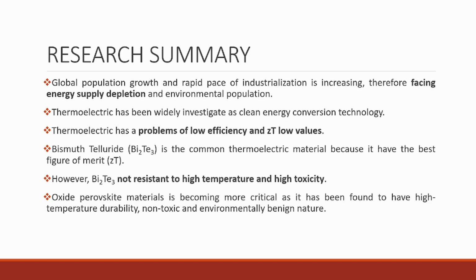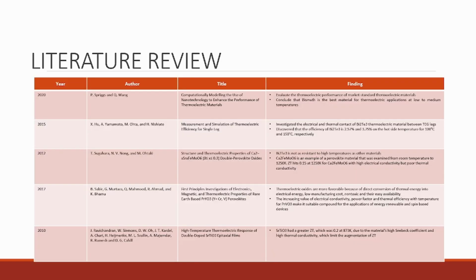Bismuth telluride is a common thermoelectric material because it has the best figure of merit. However, this material is not resistant to high temperature and has high toxicity. So another material, oxide perovskite, is becoming more critical as it has been found to have high temperature durability, non-toxic and environmentally benign nature.